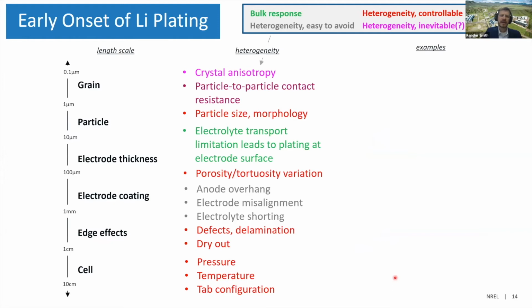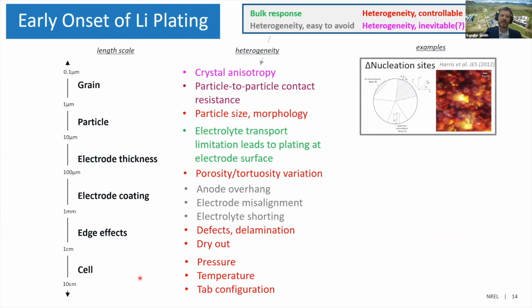Okay, getting into the heterogeneities just a little bit. This is kind of a high-level viewpoint here. There's a lot of different length scales that are involved, ranging from the grains and particles all the way up to the cell level effects. And to point out a couple of these, at the grain level or particle level, this is a depiction from Steve Harris, both for modeling, depicting the individual grains, and they each have different crystalline orientations. And so some of these crystals are going to face towards the outside of the particle. Others are going to have the basal planes pointing towards the outside of the particle, which aren't facile for transport.